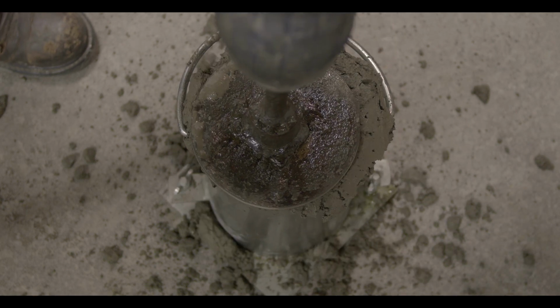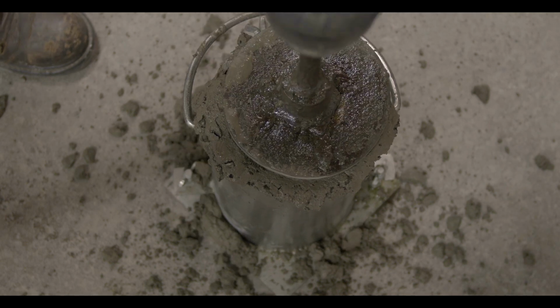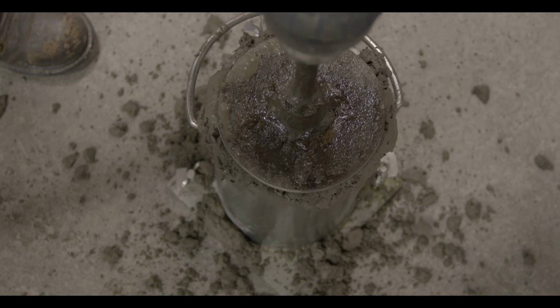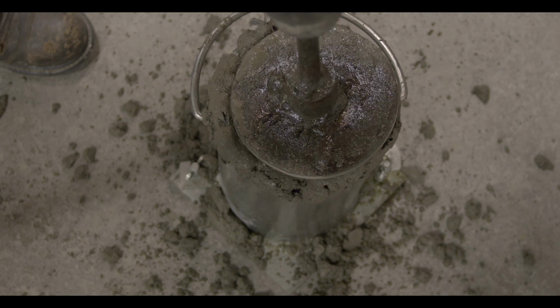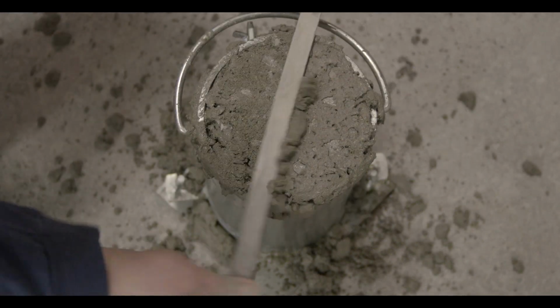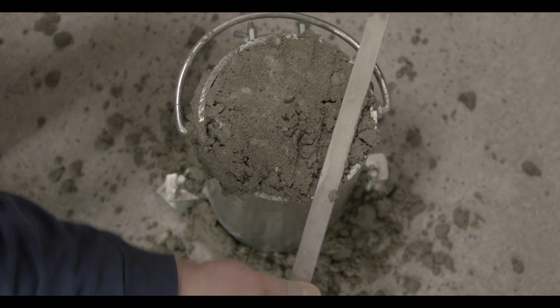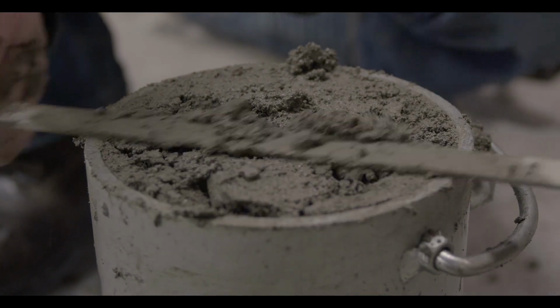With the hammer in operation and the plate in contact with the rim of the cylinder mold, move the plate back and forth across the top of the cylinder to force excess material beyond the rim. Continue working the surface until it is smooth and level with the top of the cylinder mold. Avoid tearing the surface of the concrete.